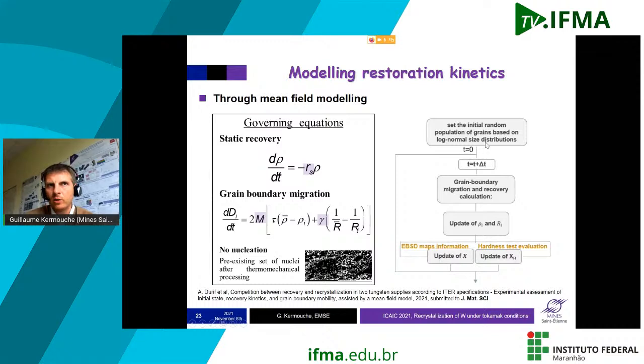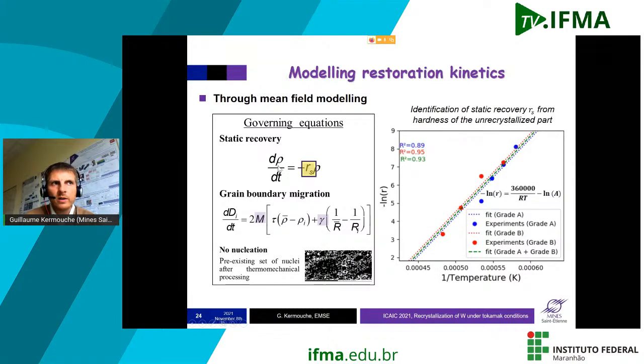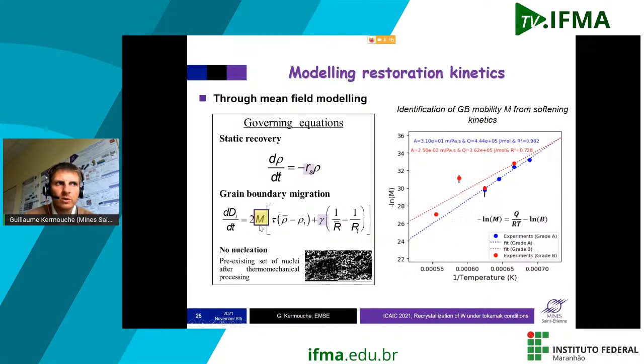And so with this algorithm, I won't detail it, we can model the kinetics. So to use this model, we need to identify this parameter and this parameter. This one is known. This one, we can get it from nano-indentation experiments or other data. You can see that for grade A and grade B, finally, this is the same recovery parameters. We have the same results. And we can deal with the grain boundary mobility in the same manner. This is almost the same result for grade A and grade B.